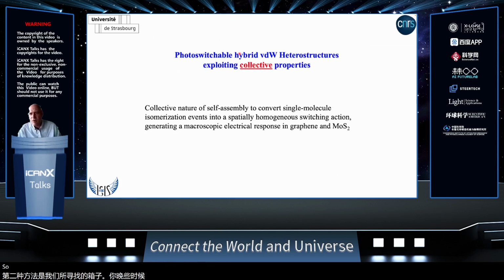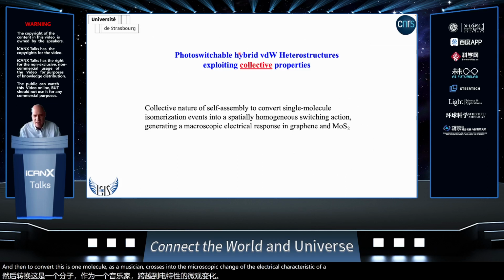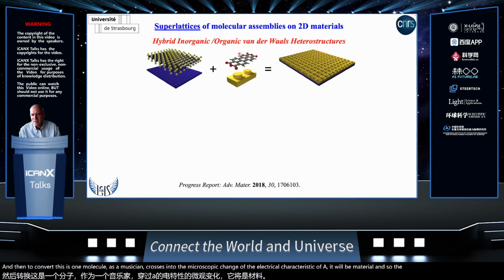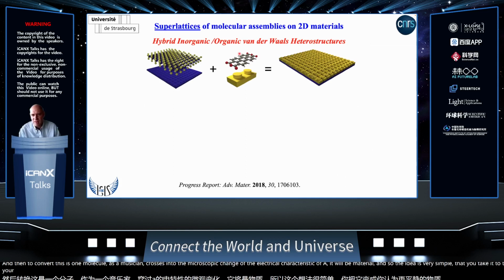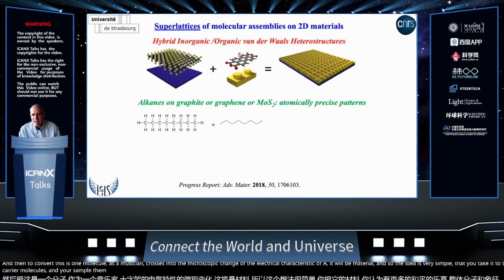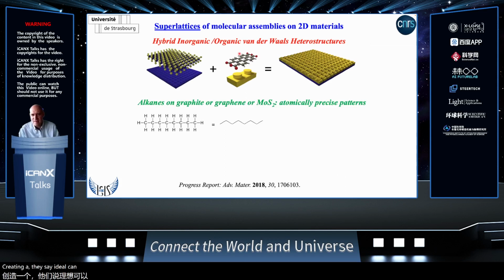So overall, the idea is that we make a hybrid van der Waals heterostructure, and we exploit collective properties in order to have a controlled self-assembly, and then to convert the single molecule isomerization process into a macroscopic change of the electrical characteristics of a 2D material. And so the idea is very simple: you take a 2D material and you take the small pieces of Lego that are your molecules, and you assemble them, creating, let's say, highly organized crystalline structures.